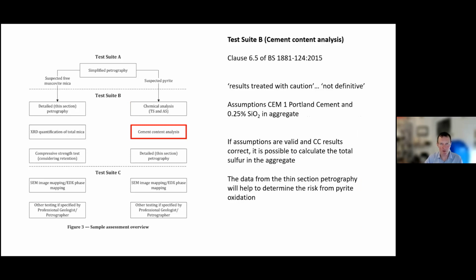There's also the requirement for cement content analysis in the pyrite pathway. And this IS465 suggests that the results must be treated with caution and are not definitive. This is because there's a lot of assumptions, or a few assumptions made on how the cement content is calculated. You can't always reverse engineer and know exactly what went into a concrete block. So sometimes you have to assume that it was a CEM 1 Portland cement and that a certain amount of silica is in the aggregate. If the assumptions are correct, the cement content results are very useful. If they're incorrect, they can be misleading.